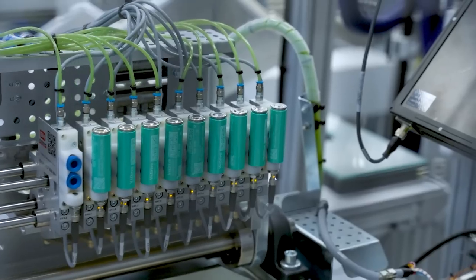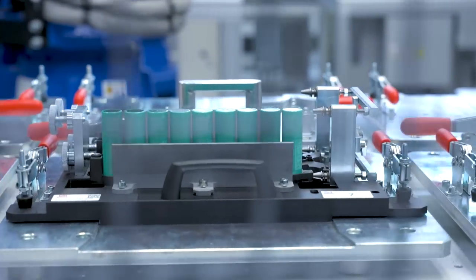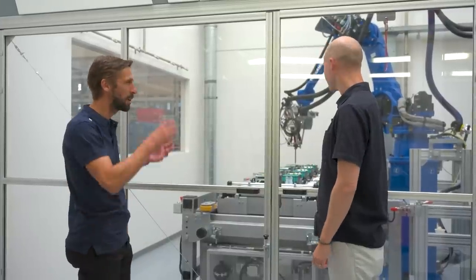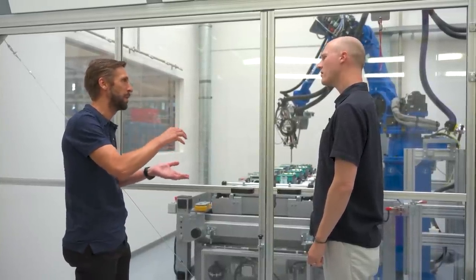Once the stacking is complete, the next step is to fix the cells — they glue them in place and then weld them together. Hubert tells me something quite amazing about the gluing room: it's temperature and humidity controlled, going from 18 to 23 degrees Celsius and 30 to 60 percent humidity, because glue behaves differently in different conditions. The cells need to be glued because they can move a little, and before welding you have to fix them in place.